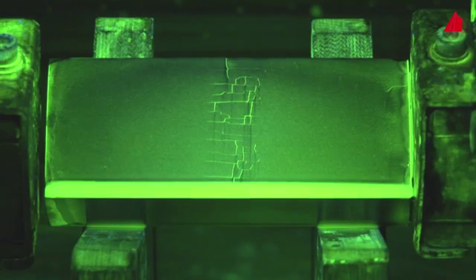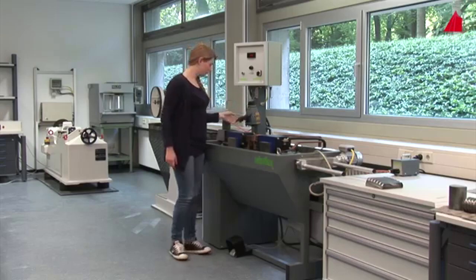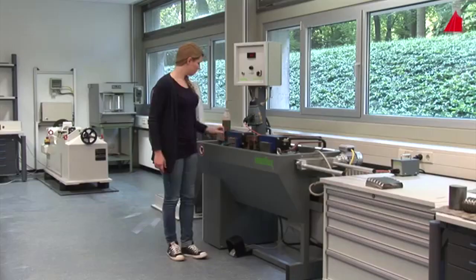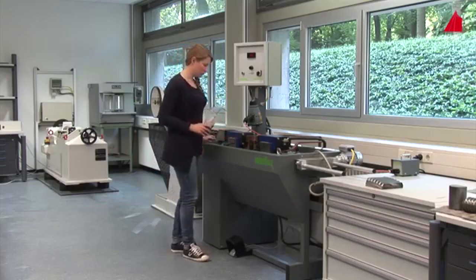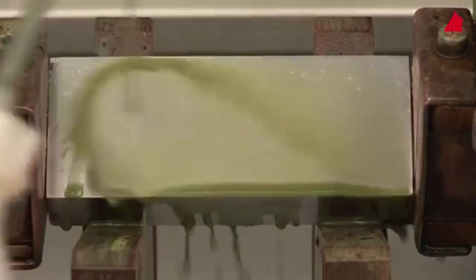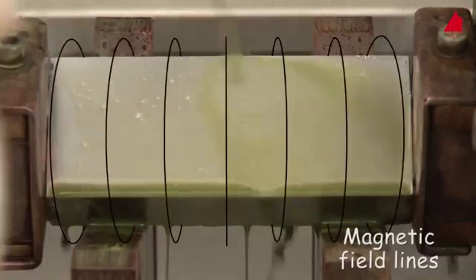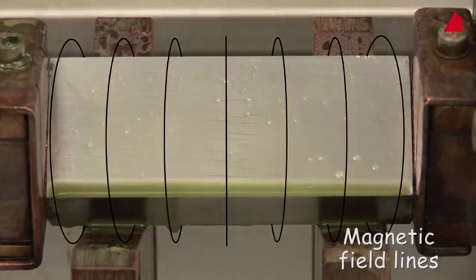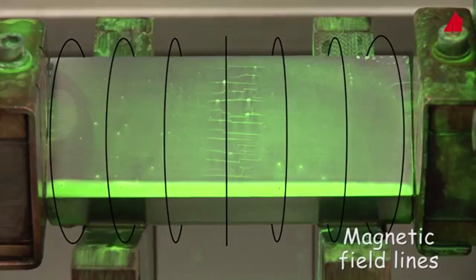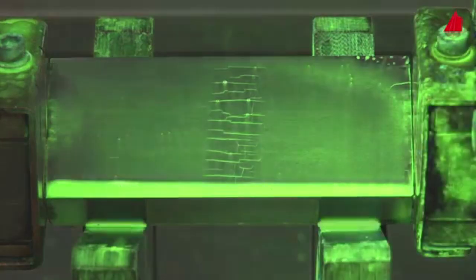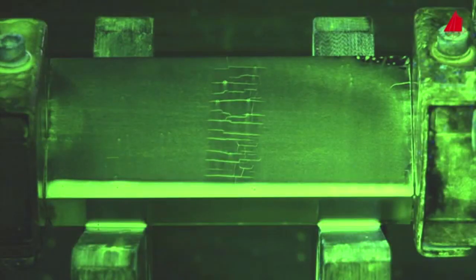the first time. To do this, the material tester switches the machine over to the current flow method. A high electric current flows through the sample, generating a circular magnetic field. Now the cracks in horizontal direction can be seen very well. The tested sample is a hardened sliding guide. The cracks have been formed during the hardening process and the subsequent grinding operation.